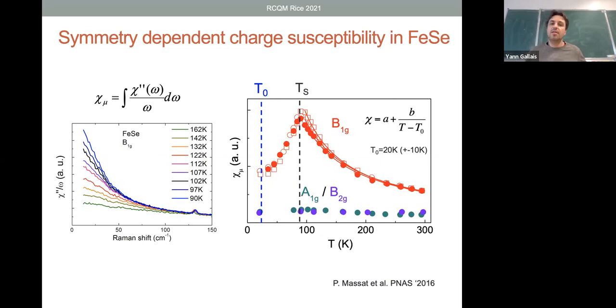So if you do that as a function of symmetry, this is what you obtain on the right. So you have a static susceptibility that is resolved in symmetry. So you can do the same operation in all the different irreducible representations. So in red, you see B1G, which follows approximately Curie-Weiss-like behavior. And in purple and blue, you see the other symmetries where it's essentially flat and featureless.